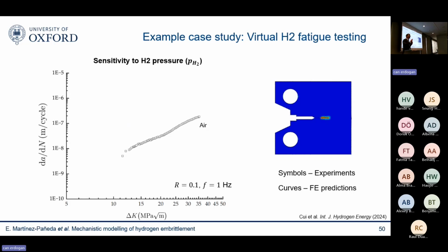So first we said, okay, we understand that you have a phase field fatigue model that relies on 2 parameters that you don't fully understand. These 2 parameters, I must confess, this is a growing field. We know they quantify the susceptibility to cyclic damage of a material, but I don't know very well what they mean. It's not like Young's modulus. So they said, okay, we're going to give you the data in air. This is for a pressure vessel steel. And I'm going to let you fit those 2 parameters.